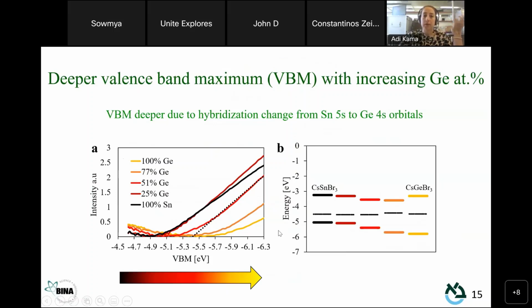When we're talking about material for solar cell, we want to know a bit about the energy alignment of those systems. So we performed photoemission yield spectroscopy measurements to measure the ionization energy of those materials that reflects the valence band position. We see that with increasing concentration of germanium, we have an increase in ionization energy, meaning deeper valence band. And that's because the hybridization changes from 5s to 4s of germanium, making the ionization energy higher.